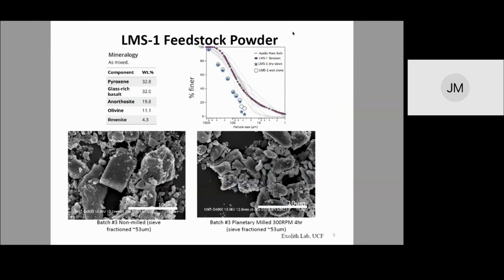So the feedstock powder that we use is called LMS-1 from Exolith Labs at the University of Central Florida. The mineralogy can be seen on the top left, as well as the particle size distribution chart in percent finer on the top right. The rings and stars are our experimental data for our dry and wet sieves that we have conducted. And for our purposes, particle size is required to be under 53 microns.